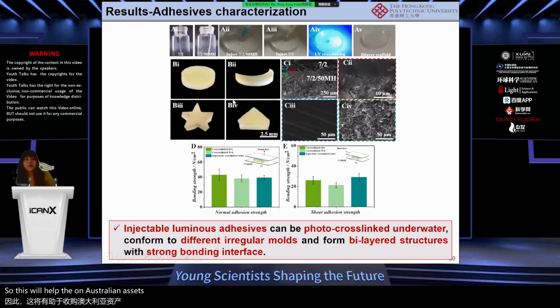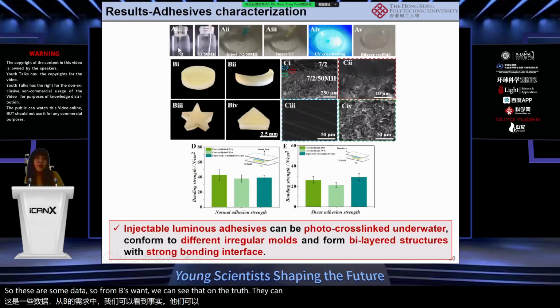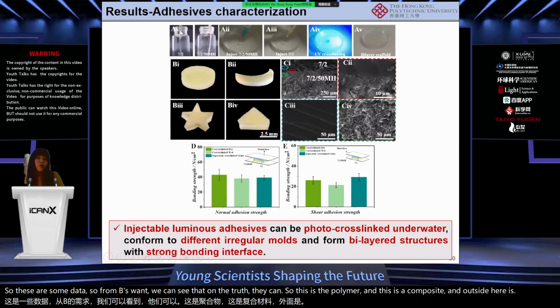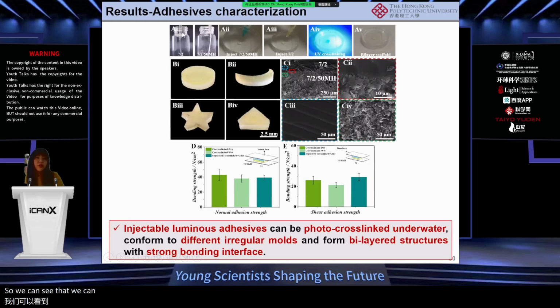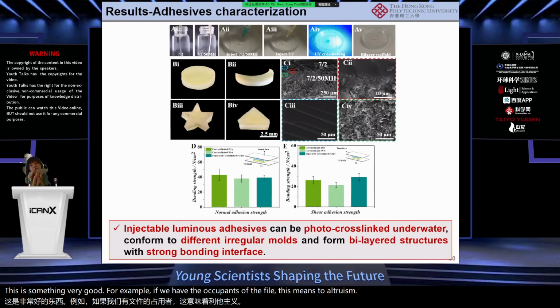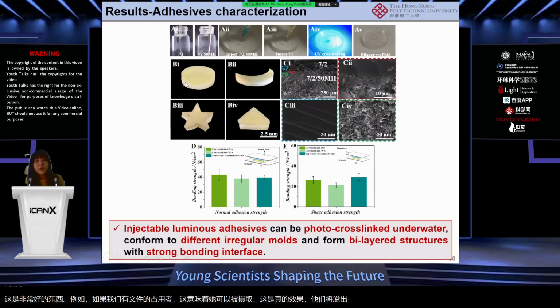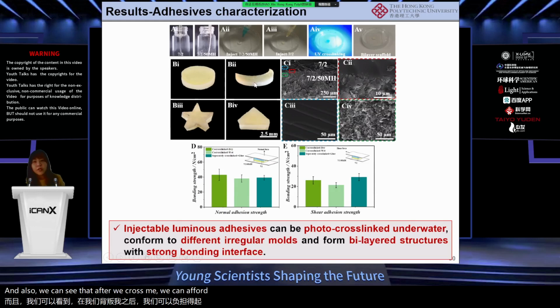So these are some data. From this one, we can see that our materials, this is the polymer, and this is the composite. And outside here is the water. So we can see that we can actually inject the materials in the water environment. This is something very good. For example, if we have the osteochondral defect, this means that our materials can be injected to the defect and they won't spill out. And also we can see that after we crosslink, we can form these kind of tight layers. So it's bi-layers, they are tightly joined together.